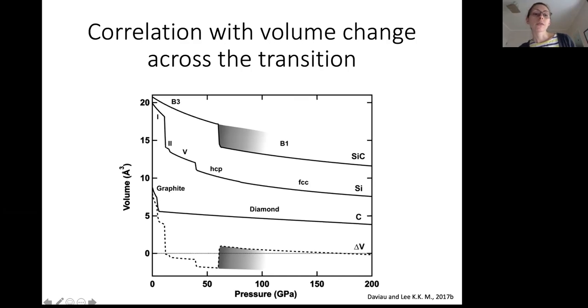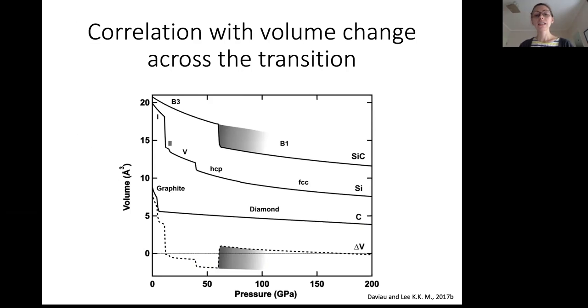So at very low pressures, when silicon and carbon are both in the largest volume unit cell structure, silicon carbide would gain volume by breaking up. The change in volume across the transition is large and positive. But after silicon and carbon have gone through these high pressure transitions, that change in volume becomes negative. So now by breaking up into silicon and carbon, the change in volume across that transition drops. This changes again once silicon carbide goes through that high pressure transition, which is shown here by this jump. And so while it's not a hard and fast reason as to why this phase diagram looks so strange, it does at least correlate very well, and so may have something to do with this kind of odd behavior.